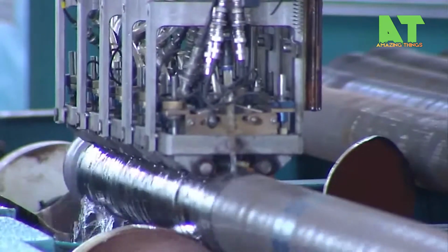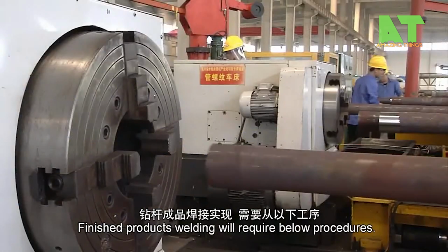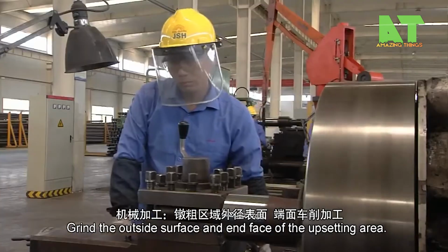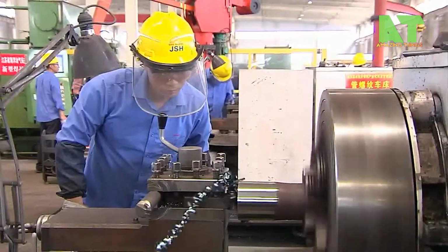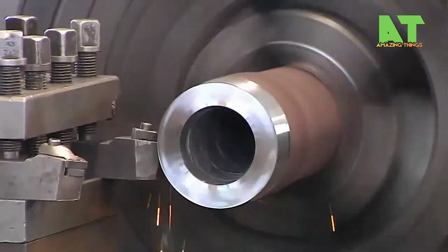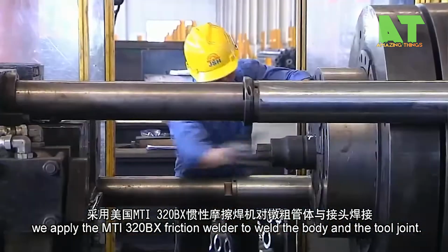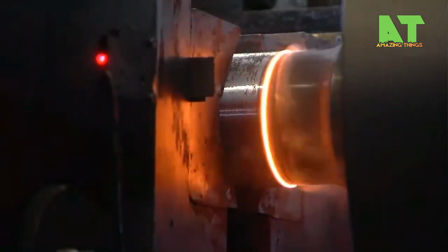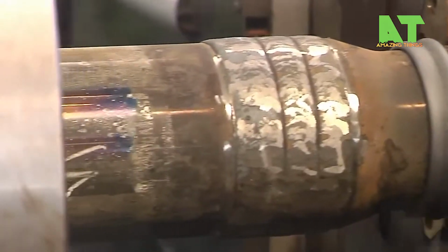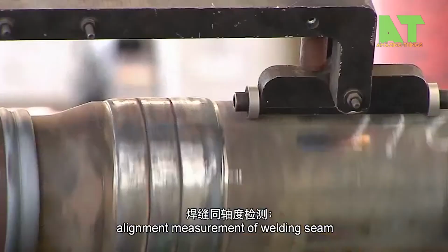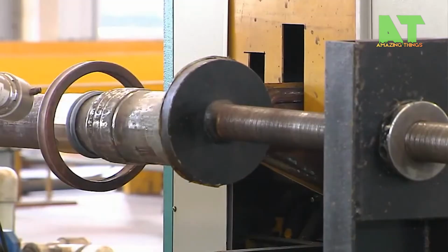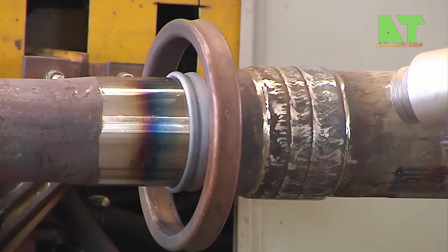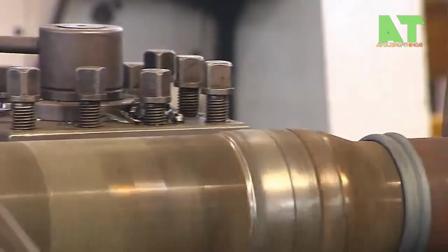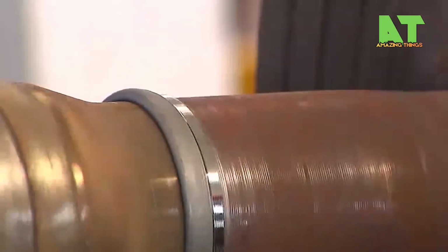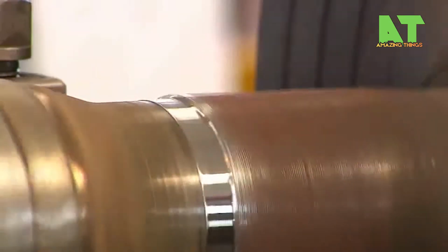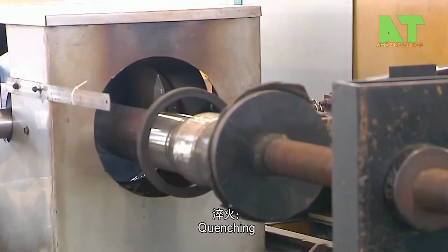This upset forging is done hot, using powerful hydraulic presses that compress and elongate the tube end under controlled temperature. Then the upset ends are rapidly quenched and tempered to achieve the required toughness and yield strength. Tool joints, the threaded male pin and female box connectors, are machined separately from alloy steel bar stock, with precision CNC lathes cutting the API or premium thread profiles that must make up reliably under field conditions. The threads are gauged to tight tolerances and phosphate-coated for corrosion protection.